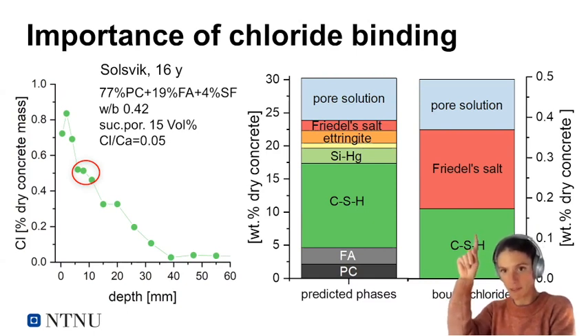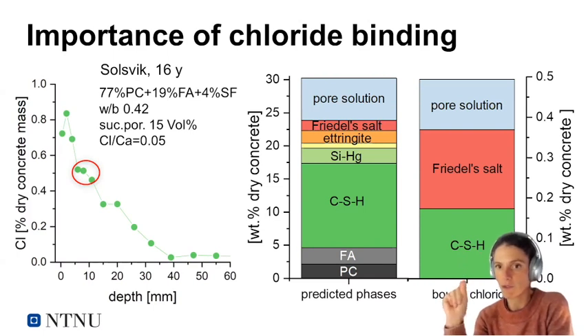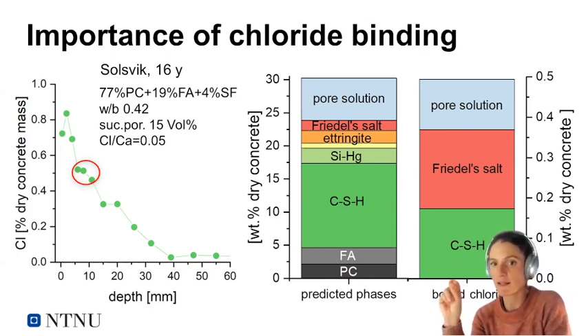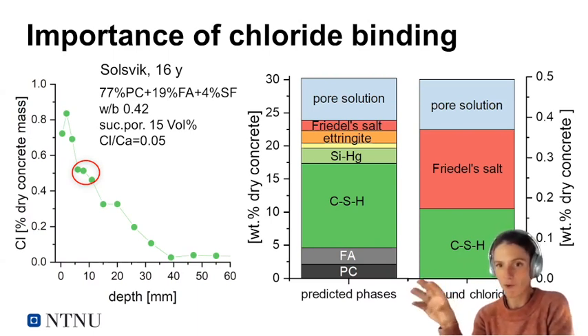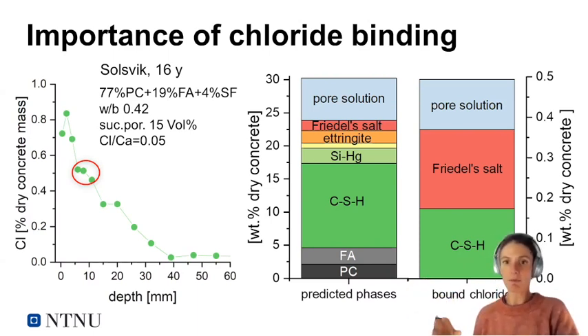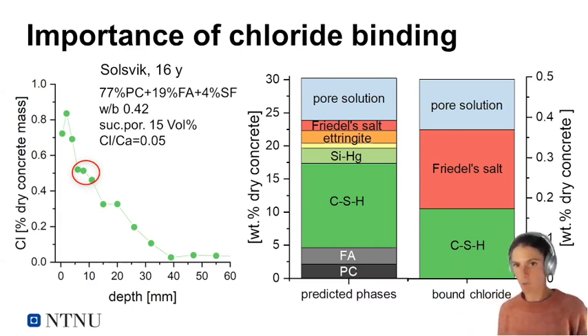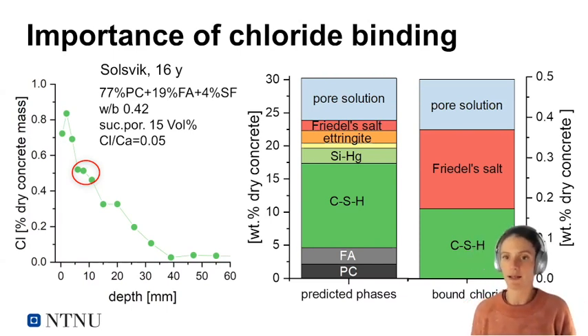So it's this that is marked in this graph above, the pore solution. If we fill all porosity with a solution with the same chloride concentration as seawater, it would only represent 0.1 weight% of dry concrete. So it's only a small part which can be represented as free chlorides, the ones filling the pores if we fill all pores with seawater. So the remaining part has to be associated in one way or another with the solids.